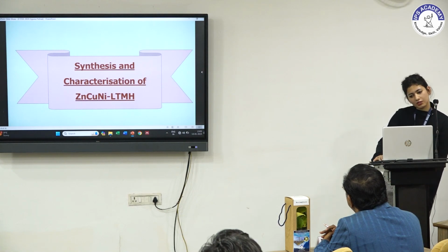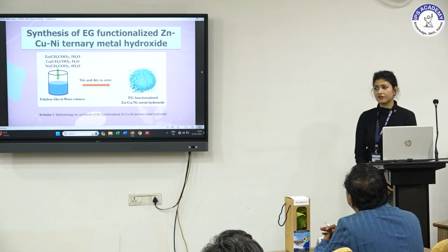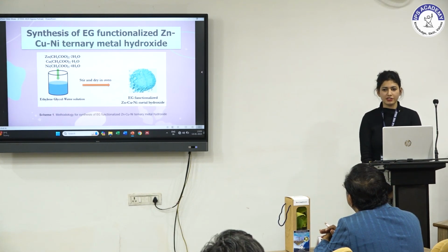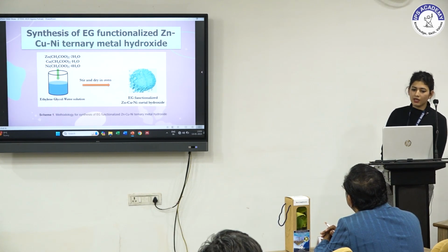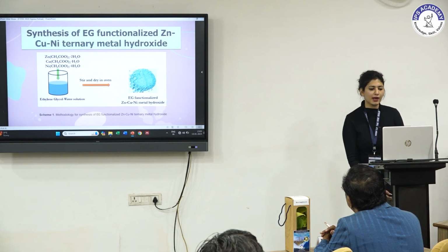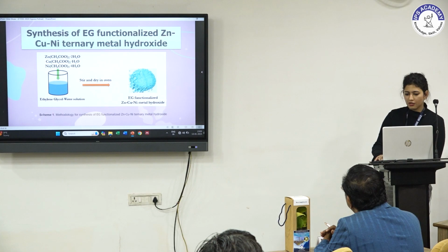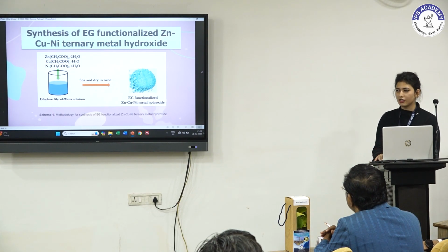Presenting the synthesis and characterization of zinc, copper, nickel LTMH, it was synthesized using a facile hydrolysis method, wherein zinc, copper and nickel acetates were dissolved in a 1:1 ratio solution of ethylene glycol and water, stirred in the oven for 60 minutes and then fully dried, after which we got a blue colored precipitate.